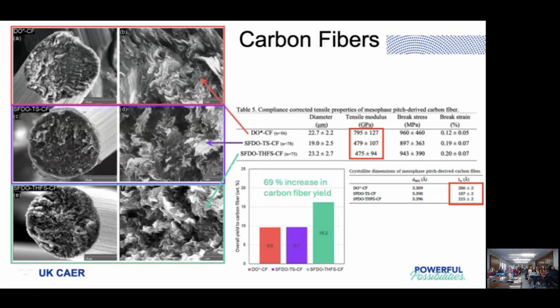But we took a hit, we took a hit in the modulus. The petroleum decant oil modulus was at 795, which is incredibly high. Remember, PAN-based carbon fibers have moduli typically around 250 on the high end. So this is 795, and with our coal extract we were about 475. But we were able to produce almost 70% more than we otherwise would.